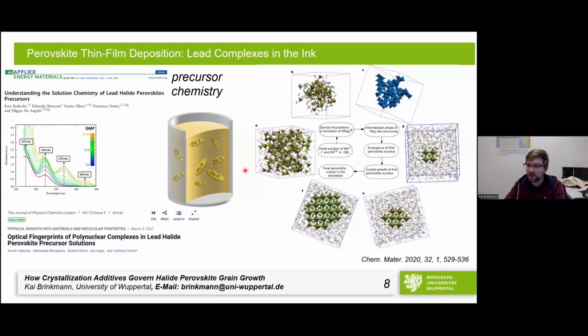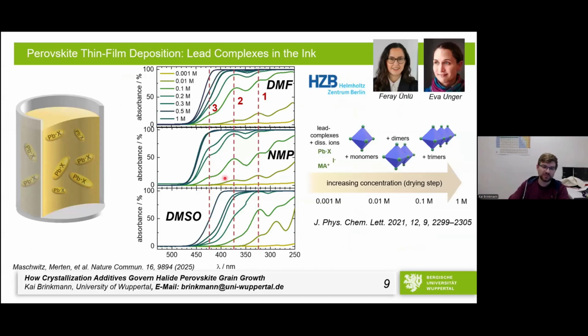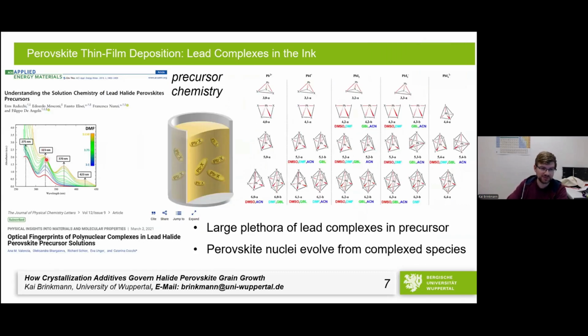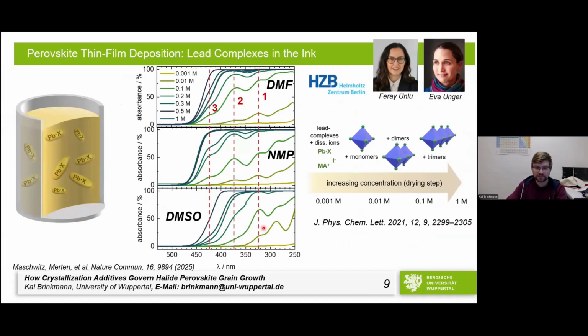But we thought, okay, we should be able to see them, right? So the first thing that we did is we performed some UV-vis measurements. This has been done by the group of Eva Unger before, so it's basically reproducing this. And one thing that looked quite nice was that in the beginning, at lower concentrations, the yellow curve here, we were able to see a very low amount of colloids. Then when we increased the concentration, we went from monomers to dimers to trimers of complexes sticking together. This aligned quite well with the drying hypothesis: if you go up in concentration during drying, you start off with small colloids, and then you eventually develop into larger grains that form the perovskite grains that we all think about.